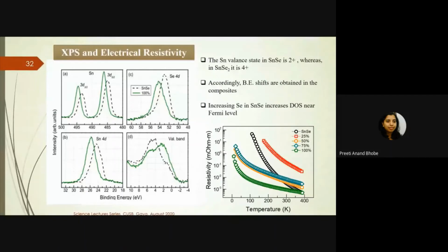Interestingly, even if one looks at the band structure, though this is not high resolution, this is generally an XPS study, so one should not really talk about valence states here. But even if one tries to look at the region around the Fermi level, then one sees that in pure SnSe, the density of states is less compared to the mixture. Here is your Fermi level, the 0, and you see that the density of states for the green curve, which is the mixed phase, is higher than that of the pure phase, which is the black curve.